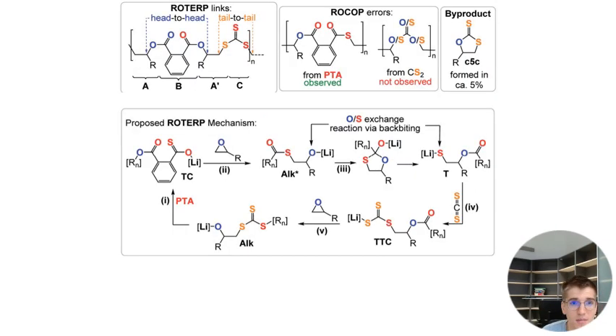Okay, so just to repeat, this was the structure that we formed, which formed in a so-called head-to-head, tail-to-tail selectivity. So the CH2 is, people term the tail position of the epoxide, and the CH with the substituent, people term the head position of the epoxide. And the ester were always next to CH positions, and the trithiocarbonates were always next to CH2 positions.